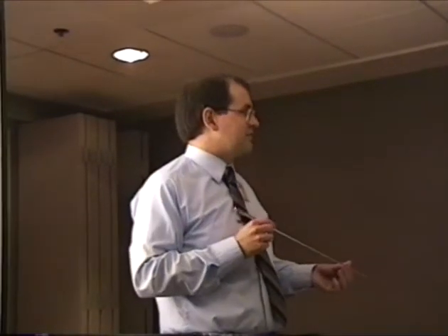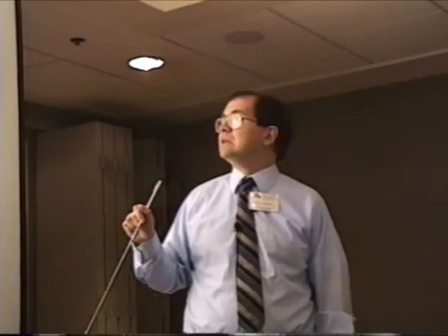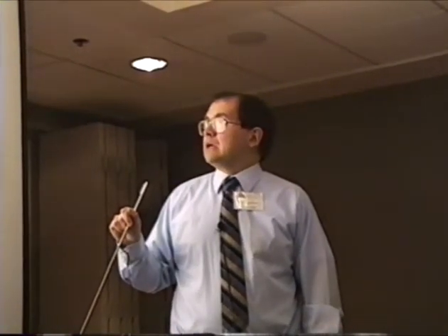Eventually, we tired of that and decided to try and figure out what was going on. You open up the catalyst and look at the actual catalyst bed, and it's covered with a beautiful, clear, waxy deposit. We can take that deposit and have it analyzed, and by golly, it's a wonderful Fischer-Tropsch wax. Starting at about a carbon number of C24 going up to C48, wonderful distribution peaking at about C28, so it goes up quite dramatically and then tails away. So we're doing Fischer-Tropsch synthesis, but that's not what's plugging the reactor.